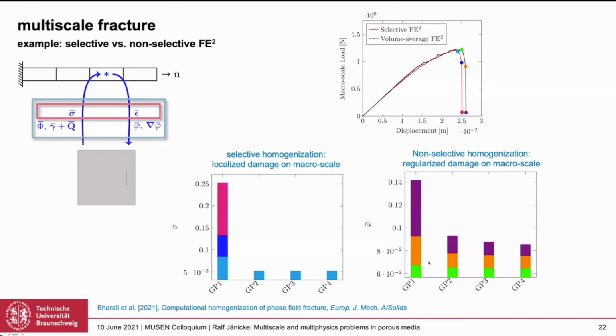And in a non-local case, we're following this black path from the green, orange to the dark purple stage. And then we see that damage is growing everywhere, even though more here, but you see that there's a certain profile. That's what we typically would also expect for a non-local damage model.